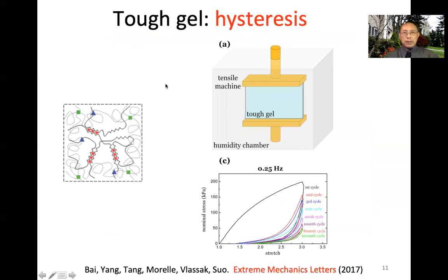Now, this is our tough gel, with calcium crosslink and also with polyacrylamide. This is a mixture of two hydrogels, polyacrylamide and alginate. Remember, the toughness of the gel is very high, 10,000 joules per meter squared.